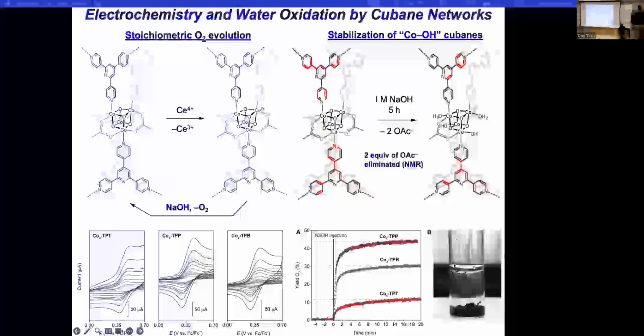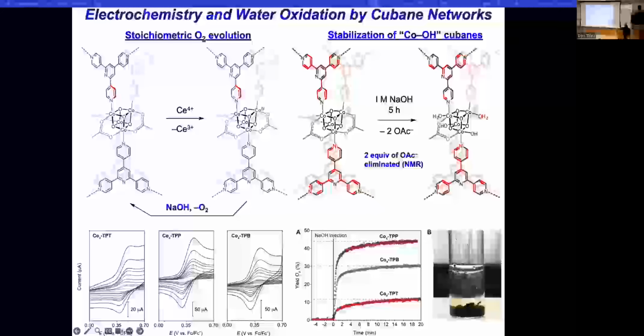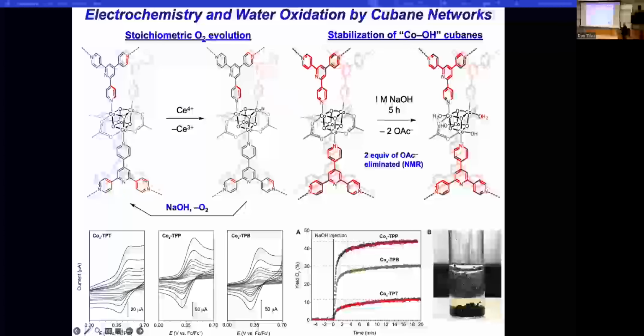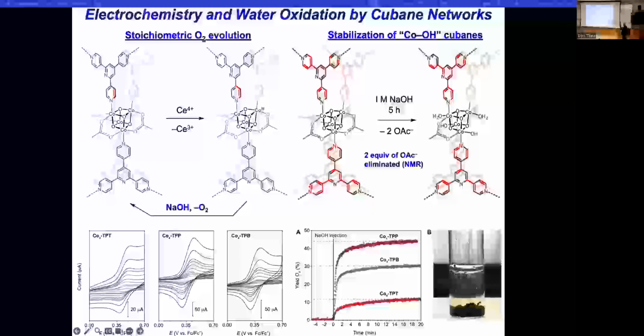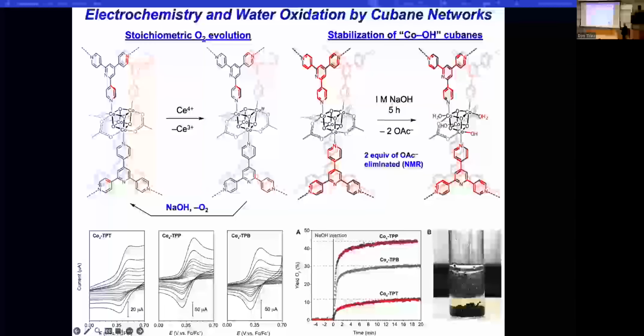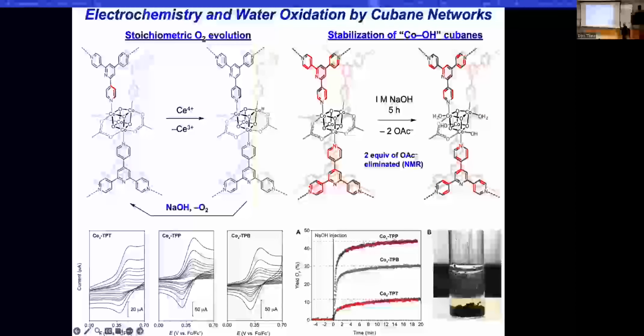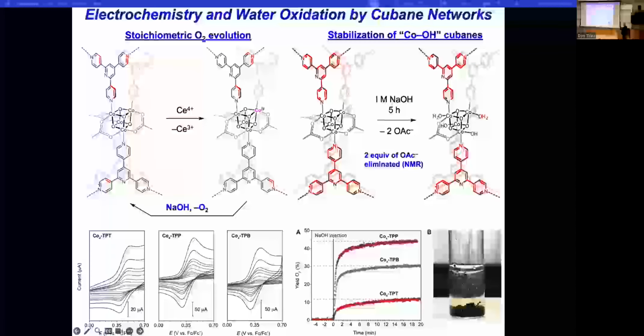Okay, so you can oxidize them, and you see some of the corresponding electrochemistry down here. You can then add sodium hydroxide. You can see oxygen. So the behavior is very similar to that in solution. And you can strip off the acetate by just washing in sodium hydroxide solution. That gives a very active form of the cubes.